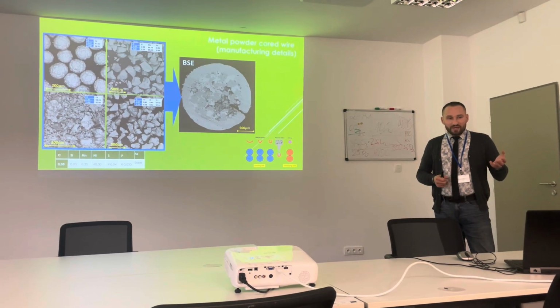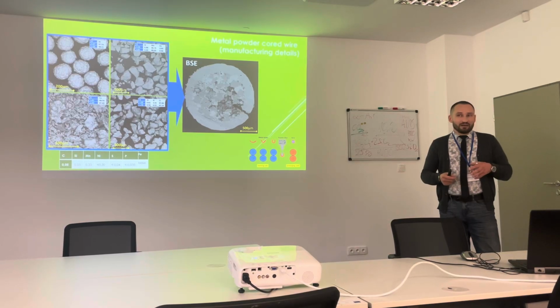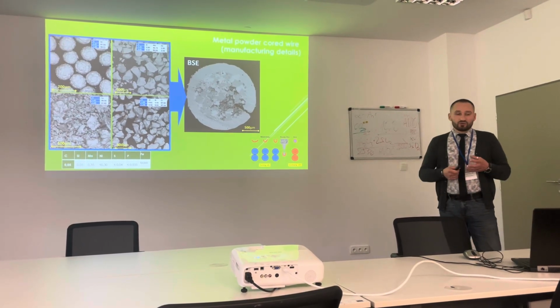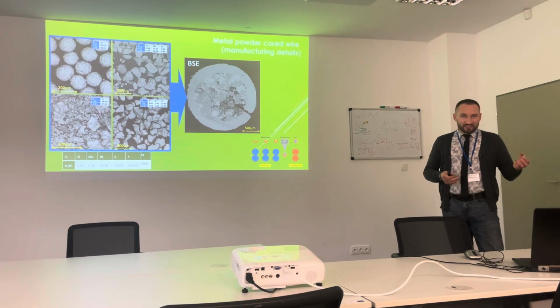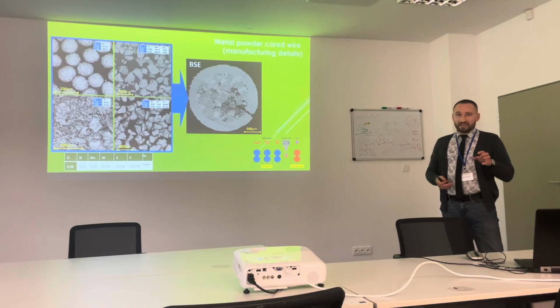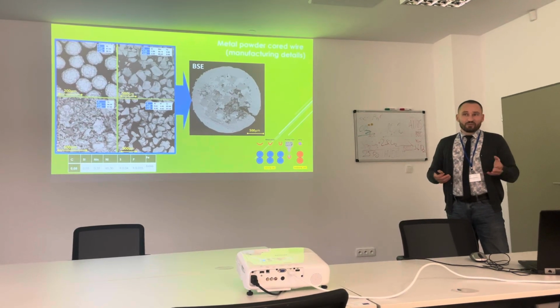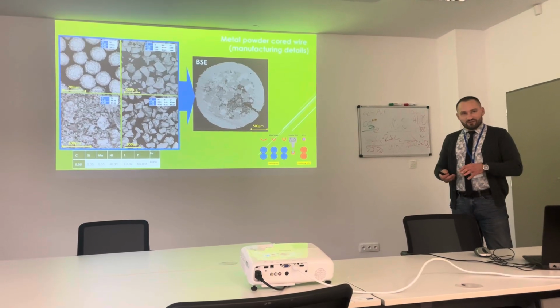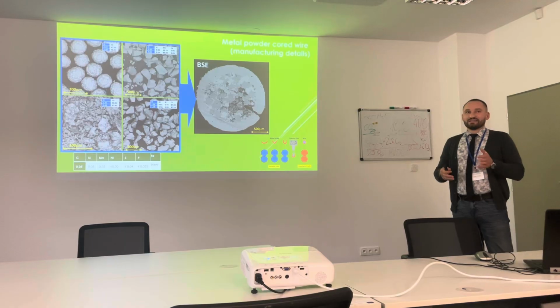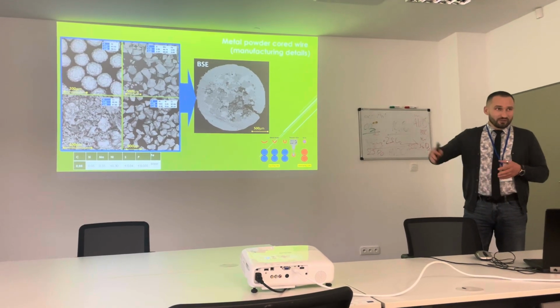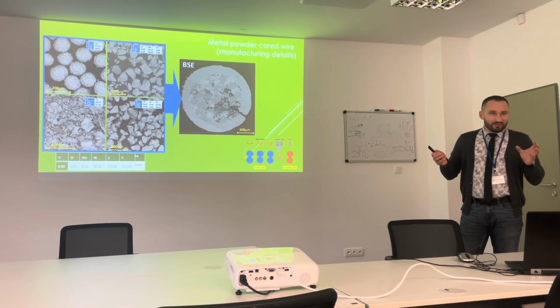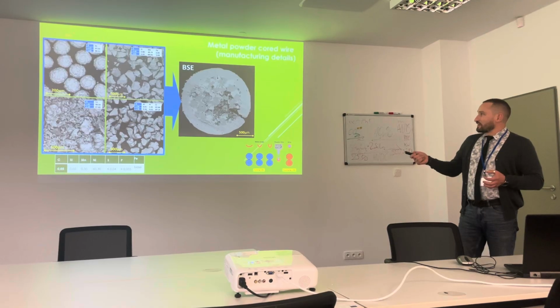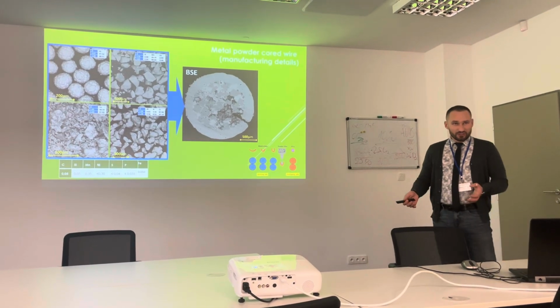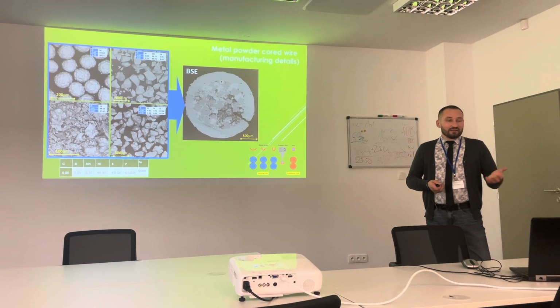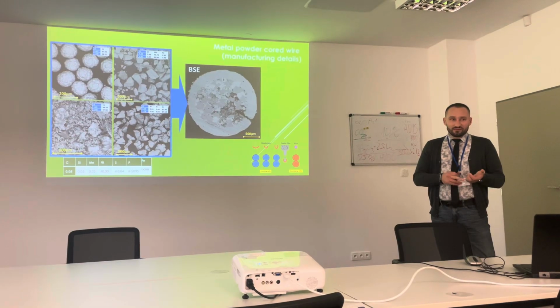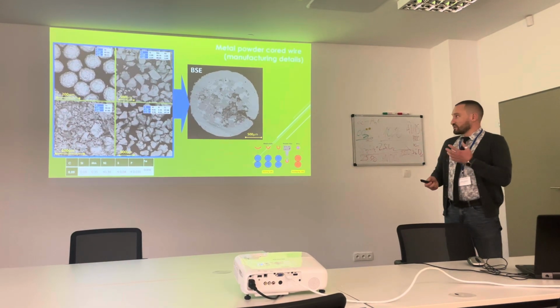This is a unique approach. Why? Because if you want to create some hard material with solid wire, you should perform drawing. However, if you have a very hard material, it is impossible to draw it to small diameters such as 2.4 millimeters, because of strain hardening and cracks, or even if you do not have cracks, you should perform intermediate softening annealing. So the price of such material will be costly. In our case, we create metal powder cored wire. We can govern the composition inside the wire, actually the chemical composition of the final products. And we needn't intermediate softening annealing, we needn't vacuum or argon atmosphere. So this is our benefit.